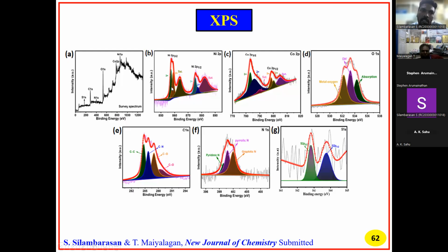Next, the XPS. Here, in figure A, the survey spectroscopy shows sulfur, carbon, nitrogen, oxygen, cobalt and nickel, all these elements confirmed in the survey spectrum. Figure B is the nickel 2p, figure C is the cobalt, and figure D is the oxygen. Then figure E is the carbon, figure F is the nitrogen, and figure G is the sulfur. So all these elements are confirmed here.